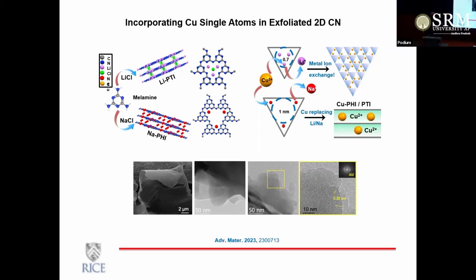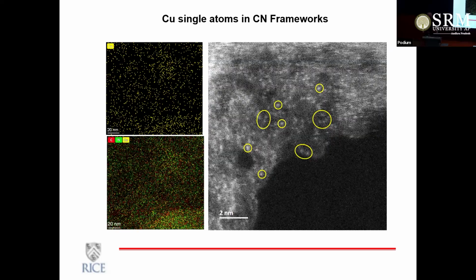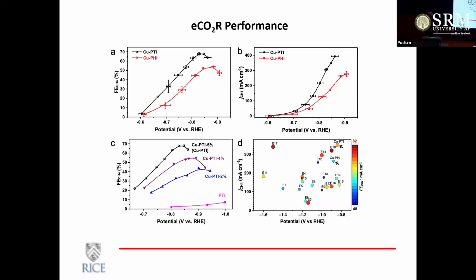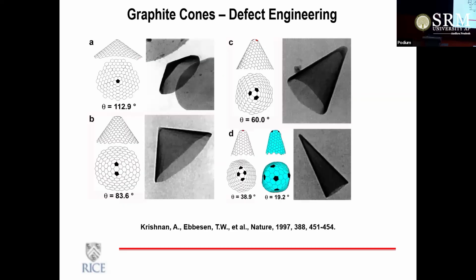You can see the holes in the carbon lattice, and you can put 1, 2, or 3 metal atoms. We have been looking at catalytic performance, whether you have one atom or a tandem effect when you have two atoms next to each other. Essentially, we are controlling the positioning of atoms in lattices so that you have the ideal case with the minimal amount required and the maximum efficiency of the reactions. By microscopy, you can detect the positioning of individual metal atoms in these lattices. It is clearly shown that for certain reactions in CO2 reduction, where selectivity is the most challenging, in this particular case of CO2 to methane reduction, this type of catalyst seems to work very well.